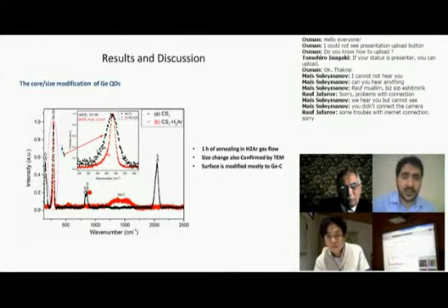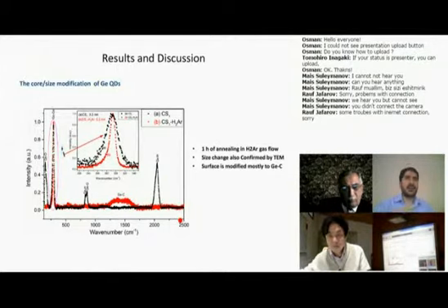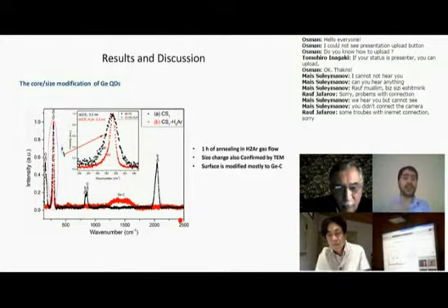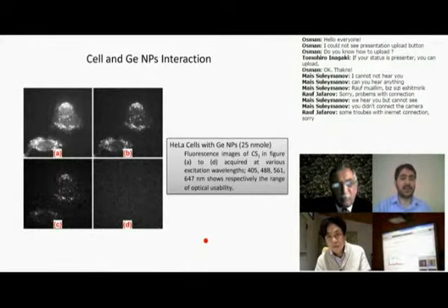This is the Raman spectra. There is a germanium hydrogen peak here. But after the annealing, this hydrogen is removed, and there is a peak which indicates that it is the germanium carbon peak. It suggests that after the annealing, my particles are surrounded with carbon atoms, and it's easy to apply any medical or biological precursor like ligands and other stuff basically.